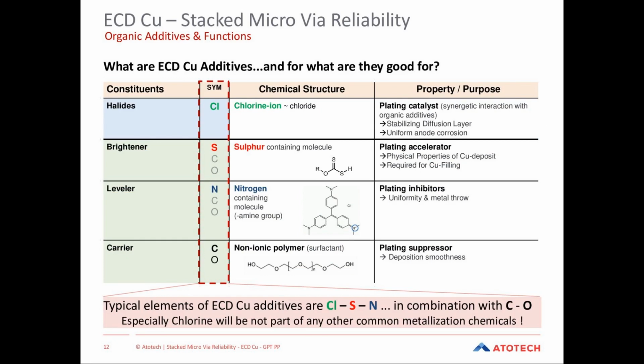Here you will have an overview about the typical plating additives which are used in the industry for copper filling of microvias. Starting with chloride ions, these are very important in copper plating processes as a complexing agent for the other organic additives we are using in electroplating of copper. Chloride ions are in a very low concentration in the solution, but very important for complexing the organic additives.